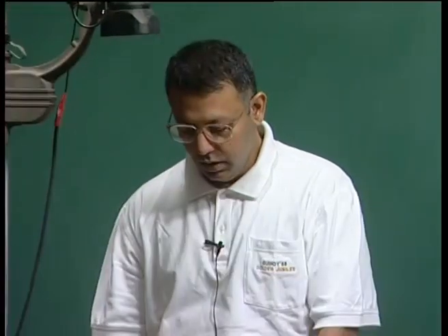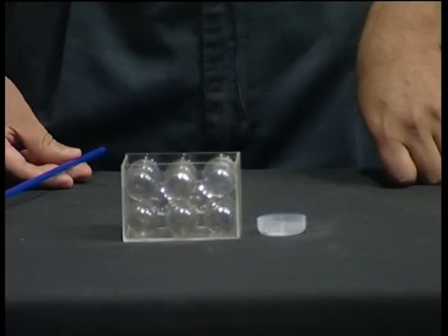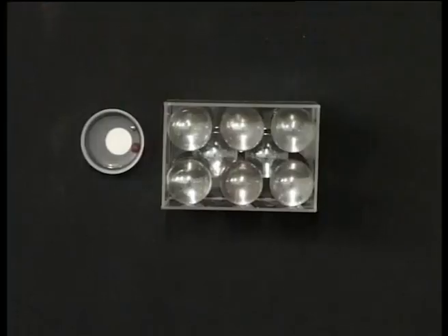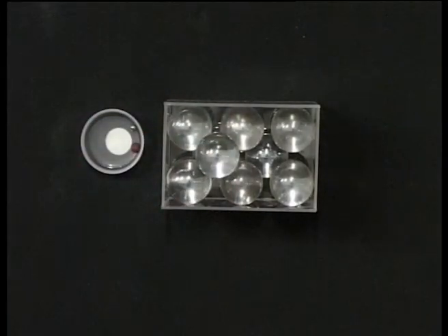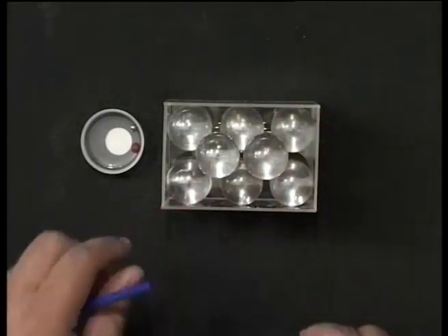So you have to remember this when you are actually trying to make interstitial alloys, which we will study later, that since these spheres which can fit into these voids are rather small, the solubility of some of these is very limited. So let us once again use these transparent sphere models to understand the relative sizes of the atoms which can sit in the octahedral and tetrahedral voids in the BCC crystal. So I have shown here two unit cells of the BCC crystal, wherein I have atoms which sit in the body centering positions, and these atoms sit on the vertices of the cube. Of course, I could grow this crystal further by putting more of these spheres along the vertical direction. So this would again be body centering positions.